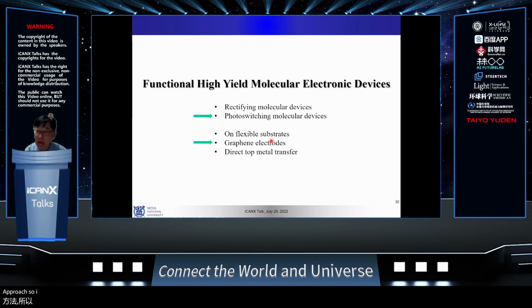By using a high-yield approach, we don't have to fabricate 10,000 junctions anymore. Even 100 junctions is enough. Even 50 junctions is enough, if the yield is 80%. So let me give some examples.